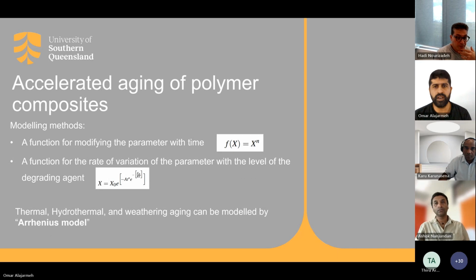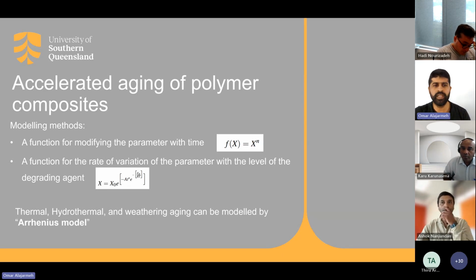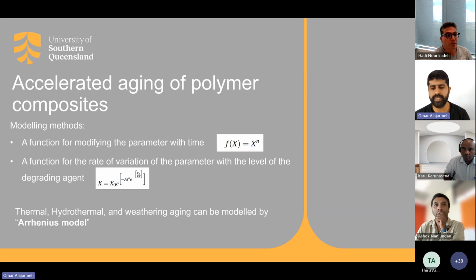So after doing testing, there is a simulation or modeling for this type of aging, and mainly we are looking for a function for modifying the parameter with time. This is an example of aging that comes from mechanical properties. For example, the function x to the power n is more about creep and fatigue. If you change the stress ratio or the level of load, you will get this function that suits those